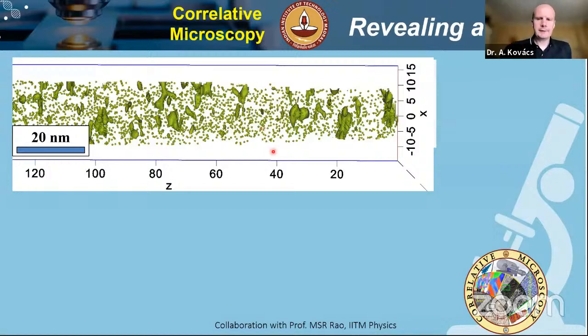Yes, so this is probably also the answer to the question of Monica Singh, because she was asking about the correlative microscopy of living cells. And probably I can comment. Living cells, as it is, probably not possible, because all of these biological samples, first of all, have to be frozen. So the cells are embedded in vitreous ice. But after that, as you very nicely explained, if you can maintain the transfer in cryogenic conditions to an atom probe and we don't destroy it before, the experiment can be successful. So I can foresee more and more applications of cells and biological applications also at an atom probe.